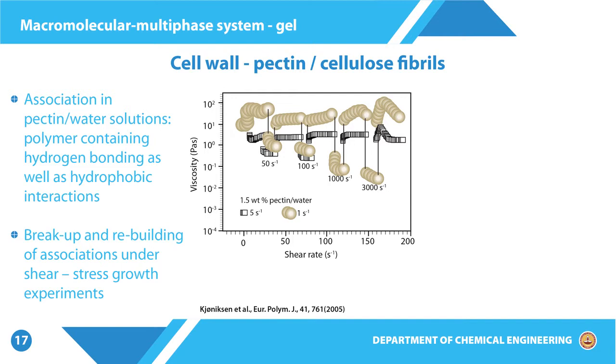Further looking at the same material with cellulose microfibrils itself, when we form a gel, calcium actually cross-links pectin, and therefore, in the presence of cellulose microfibrils and calcium we can form a gel, and we can see that the overall response is pretty much gel like, in the sense that G prime is higher than G double prime. And in this case we can see that if only cellulose microfibrils are there, properties are lower. Similarly, if only pectin is there, then properties are lower,